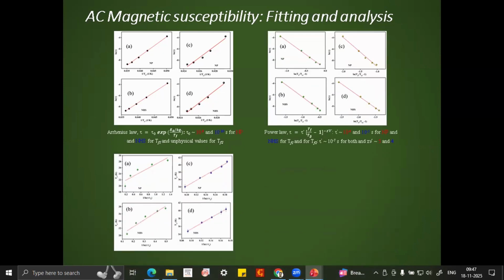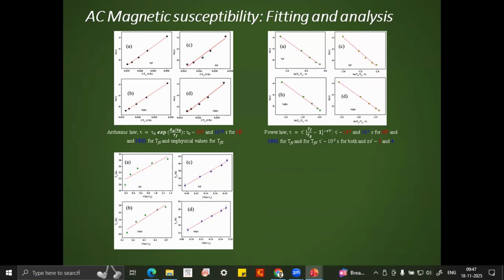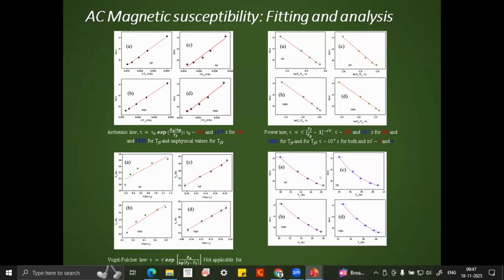Now we further proceed to other analysis of the temperatures that we have obtained from the bi-Gaussian fit. We have fitted it with the Arrhenius law. Then we have fitted it with the power law, and also taking that value of tau prime from the power law, we have fitted it with the Vogel-Fulcher law. Also, we have fitted with the Vogel-Fulcher law independently. All of the analysis shows that there can be a dominance of superparamagnetic nature in nanoparticle. On the other hand, nanohollowspheres show a relaxation time of typical spin glass. Now, these are all not very conclusive evidence.